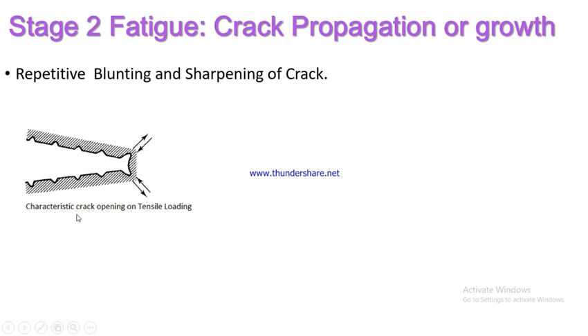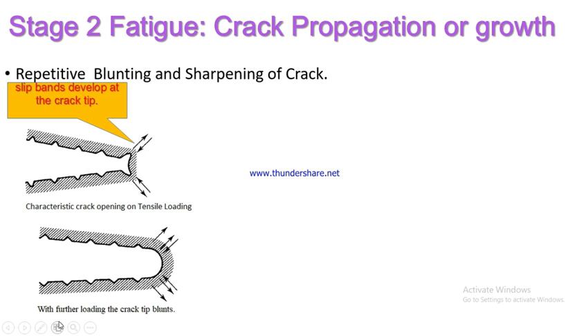The first part is what we call crack opening, or tensile loading. When those cracks begin to be under tension, when the material begins to experience tension, the slip system begins to develop. You can see the slip bands develop along the crack tips, which is here. You can see the crack tips and the slip system begin to increase, and then with further loading, the crack tips begin to blunt. So once you begin to open more, pulling the system apart under tension, the crack tip will begin to blunt, which is here.